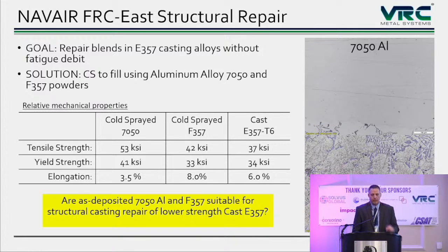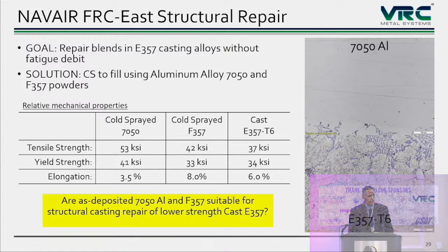So what you see here is some properties of 7050 and then F357 as repair materials for the E357 casting. What's interesting about this is you'll see the strength values of each of these materials is actually higher than the E357 substrate. So in this particular case, we're spraying on material with a higher strength than the substrate material. So now let's see how it performs from a structural standpoint.